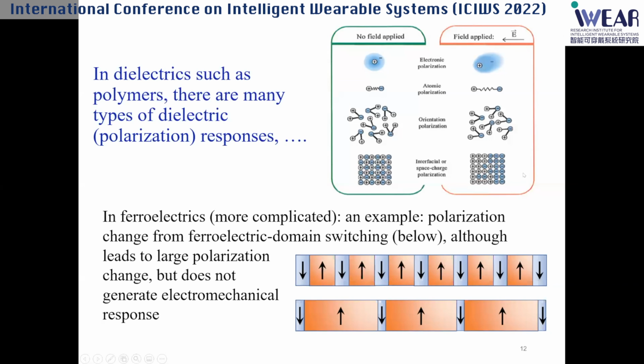Also in ferroelectrics, there are many different types of ferroelectric polarizing response. What I find is most of the times when people do research, they never ask this fundamental question. That's why we've missed this for so many years. For example, in a ferroelectric, in ceramic or polymer with those ferroelectric domains, if we flip these dipoles, flip this domain, change the direction 180 degrees from here to there, basically you increase polarizing quite a lot, but there's no electromechanical response.